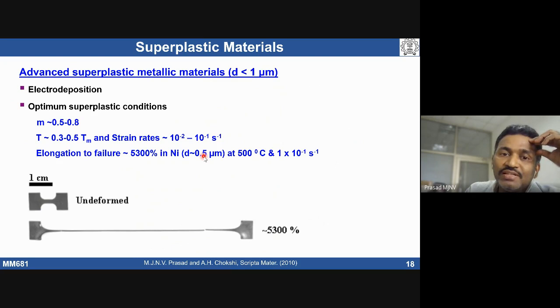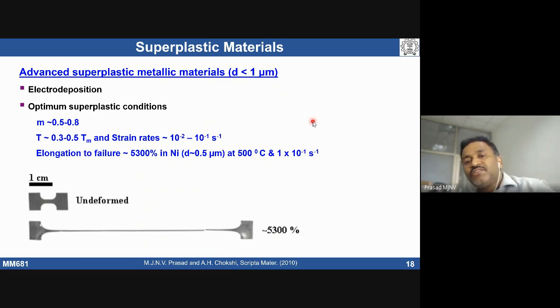So that means if you can have a fine grain size, and make the grain size stable at that temperature, we can get large superplastic elongations at high strain rate. Even at low temperatures, you can lower the temperature, because your diffusion activity is going to increase if you have finer and finer grain size. So one can also lower the deformation temperature. These come under the category of advanced superplastic metallic materials.